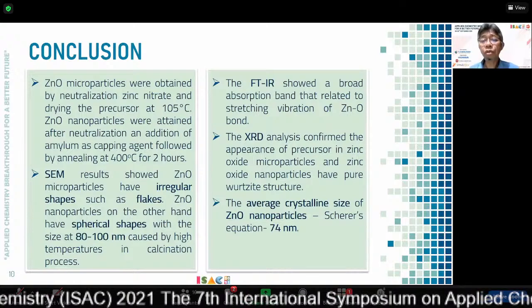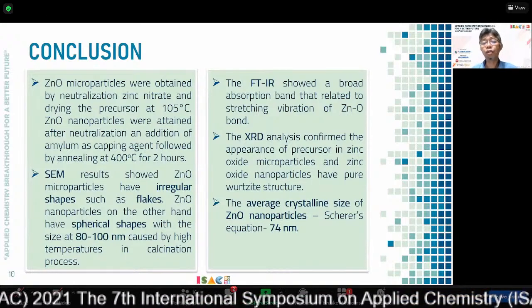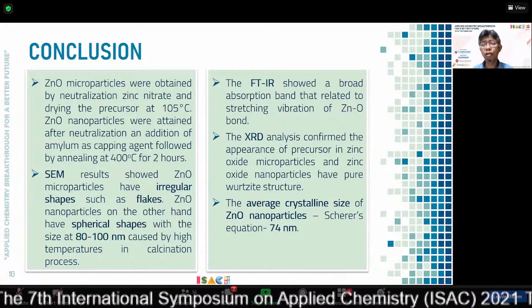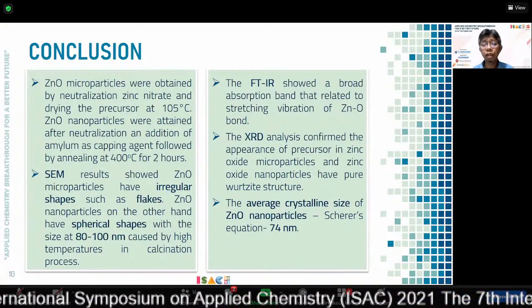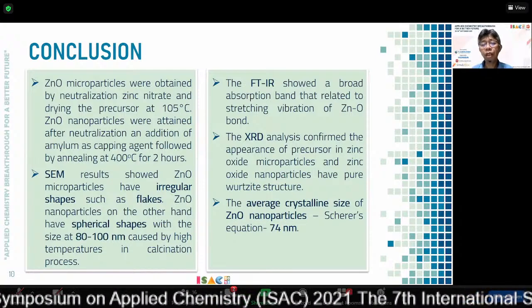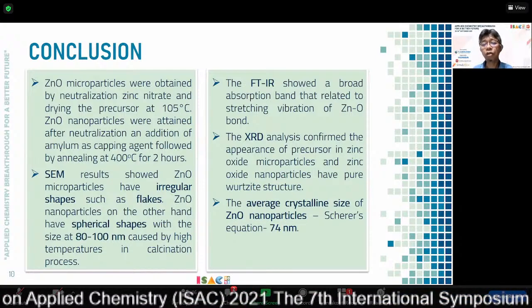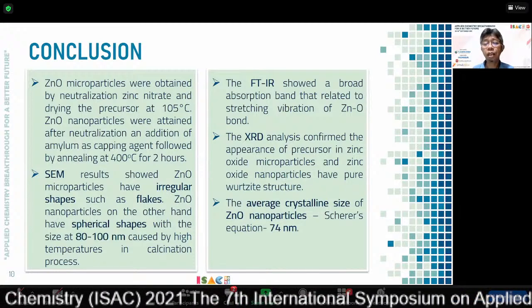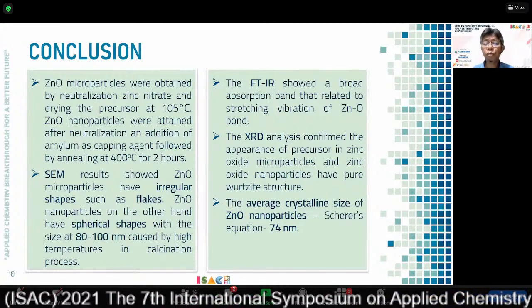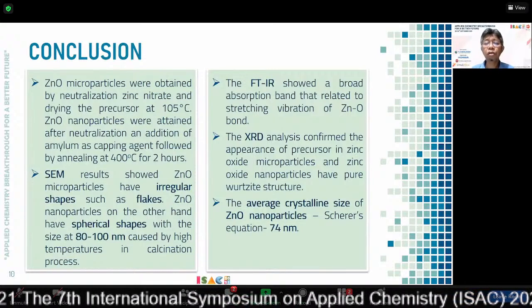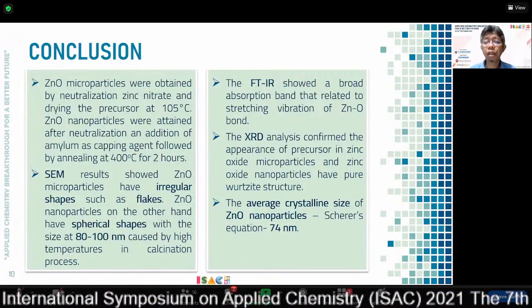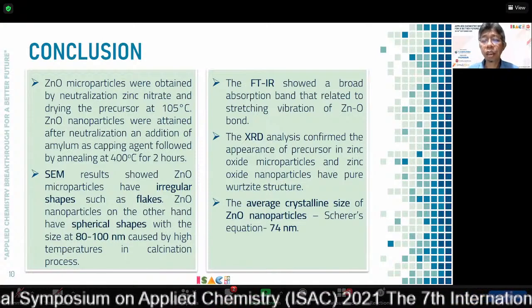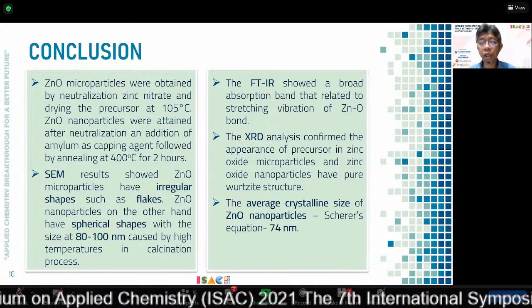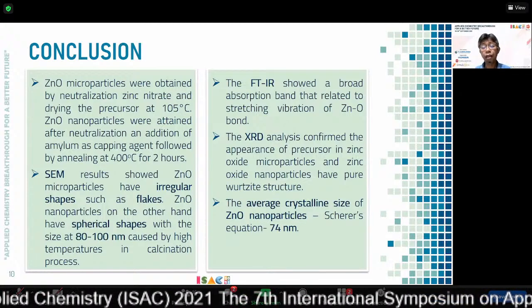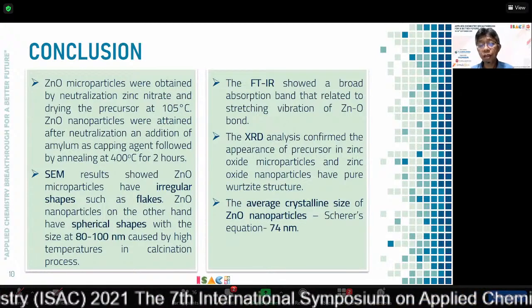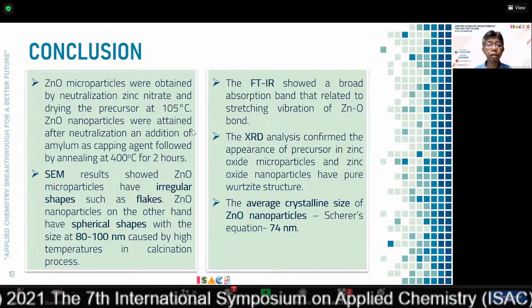The FTIR also shows the broad absorbance band related to the stretching vibration of the zinc-oxygen bond. The XRD confirms that the precursor of the zinc oxide microparticle still exists there, with only a small part being zinc oxide, as compared with the zinc oxide nanoparticles having the pure wurtzite structure. And the crystallite size is about 74 nanometers.